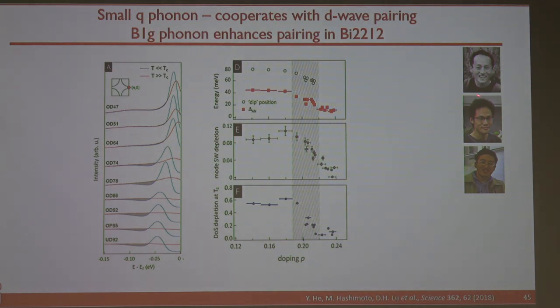So the next question is, this is the thesis work of He. Now he's a professor at Yale. And it is as a function of doping in this one. And you can see in this narrow doping range, I'm measuring here red data points, this gap of superconductivity. In this doping range of 4% change, the gap has gone from 10 millivolt to 40 millivolt. It's a factor of 4, 400% change in a narrow doping range. Okay. In this regime, 2 delta over kTc is what you expected for d-wave BCS. Okay.